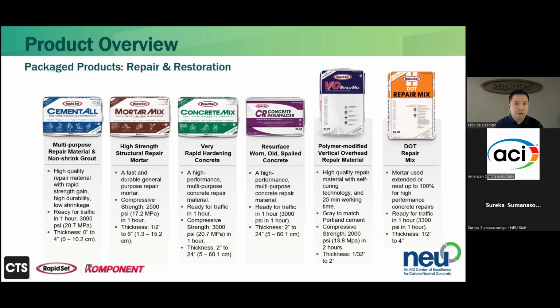With concrete resurfacer, used to restore old and spalled concrete, starting from 2 inches thick all the way up to 2 feet thick. VO repair mix is for vertical and overhead applications, as the abbreviation implies, and that has self-curing admixtures and retarders to extend working time. And then DOT repair mix is formulated to cater to higher performance specifications for DOTs, certain specifications that might be more demanding than folks that pick this stuff up out of the Home Depot might require.